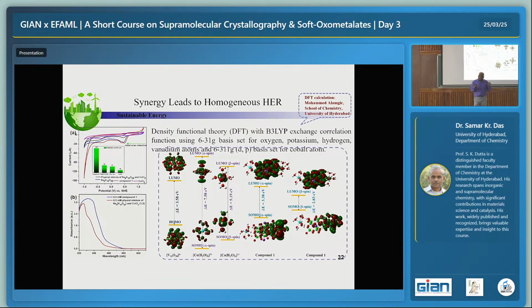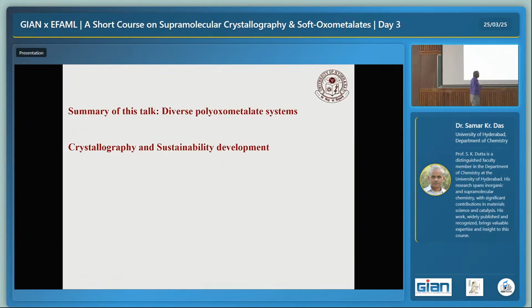So that means synergy is definitely established, because as such the compound doesn't give water reduction, cobalt alone doesn't give water reduction, even the physical mixture doesn't give. That means the physical mixture doesn't establish synergy, because hydrogen bonding establishes the synergy, and finally we can get hydrogen. So the electron comes from the machine to the cluster, cluster to cobalt, cobalt to water. This will give continuous hydrogen. This is what I want to tell you, that with polyoxometalates you can understand first of all. If you are lucky, you get a single crystal, you know the system, you apply your mind and do interesting chemistry.